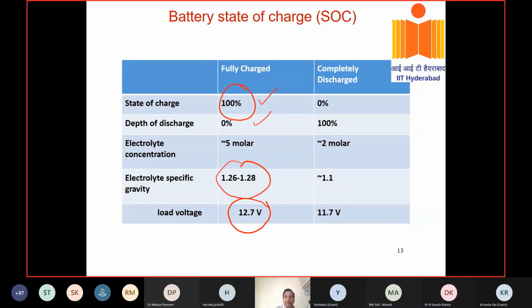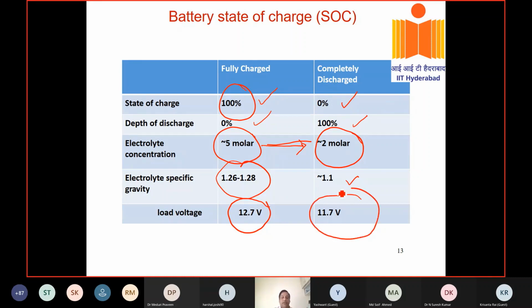And when it is completely discharged, you see there is a significant change in the concentration. This doesn't happen in the lithium-ion cell. This is in the aqueous systems. This is one of the concentration changes during charge and discharge, because water is formed during discharge. So the concentration of sulfuric acid changes to 2 molar. Again, during charge, it goes back to 5 molar. So complete discharge means you have 0% capacity, and the depth of discharge is 100%, and the electrolyte specific gravity is 1.1, and then the full discharge voltage can be 10.5 to 11.7 volts. So it's almost 1.75 to 1.95 volts per cell.